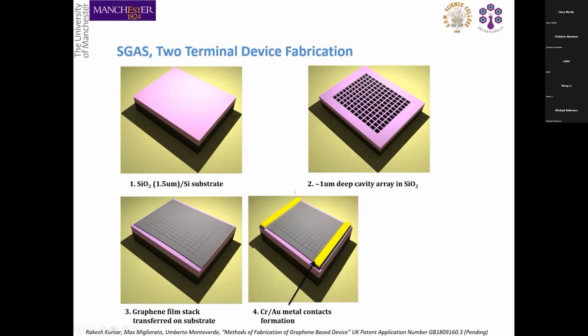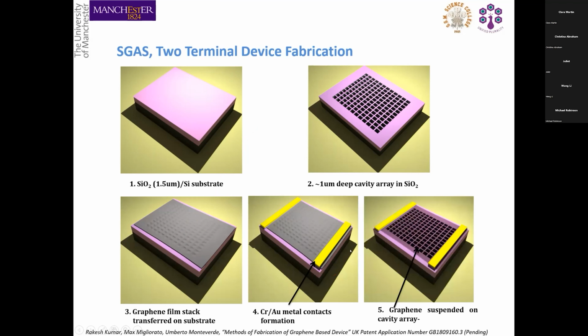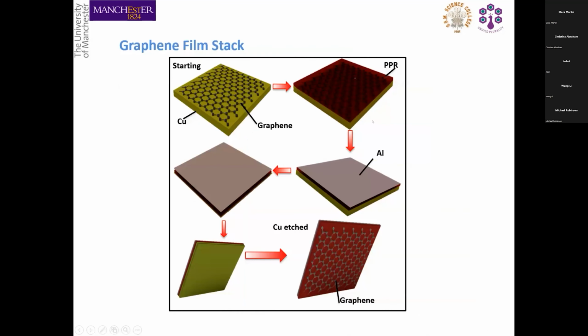So once you have the graphene, you create the metal lines on top, and then you can release the polymer or the protecting layers in order to have a graphene film on top of the cavities. So I might skip this. This is just a copper film with the graphene on it. So we transfer polymer, and then we do an aluminum deposition of around 25 nanometers on it. This aluminum provides some strength to this brittle polymer. And then once you etch the copper from below, this graphene is ready to be transferred onto the